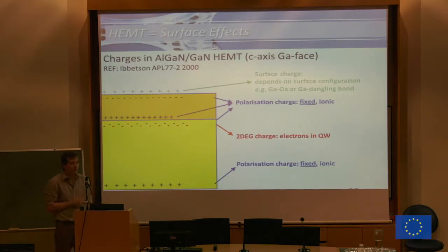And very early in the gallium nitride technology, it was recognized that these charges must come from the top surface. Now there is one issue with this, the fact that your charges of your electron channel come from the top surface, and that is that if somehow during your processing or during operation or whenever you change the charge on the top surface, you will immediately also change what's happening inside your transistor. And that, of course, is an effect that you do not want.